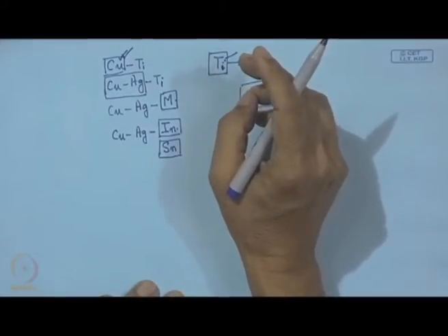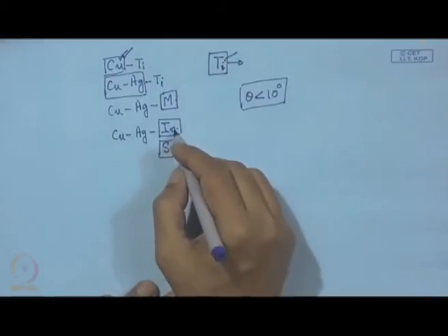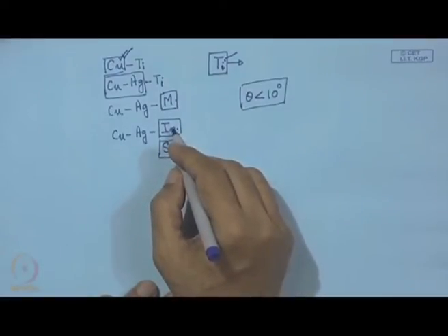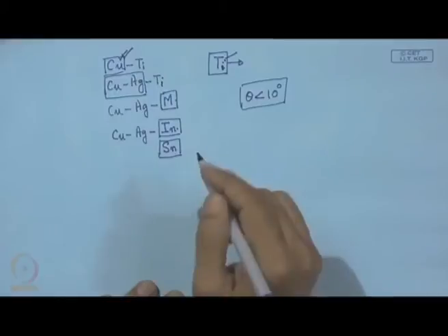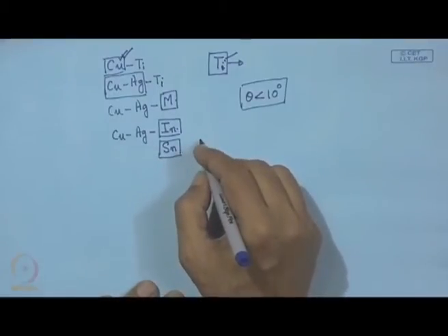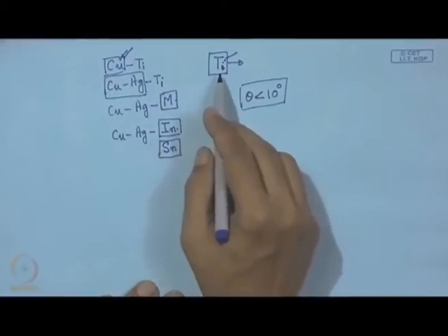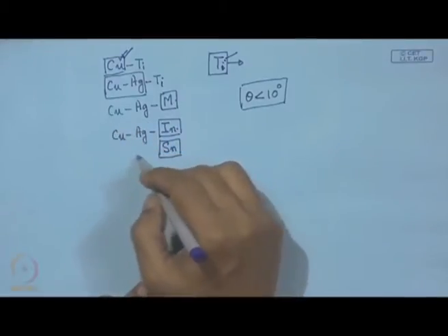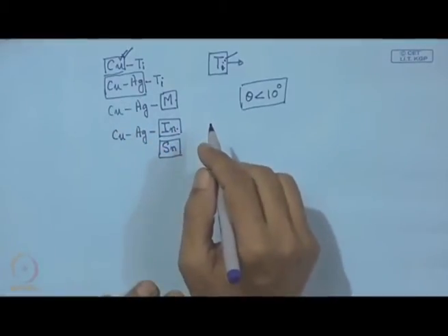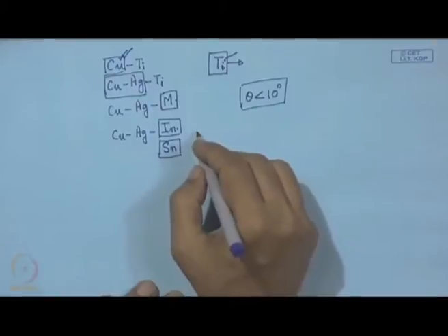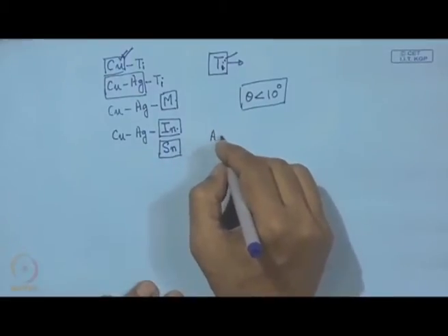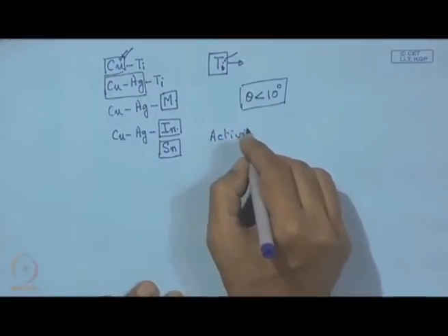Exactly what does it mean? When we add indium in this system, what happens? The solubility of titanium in this alloy decreases, and thereby the activity of titanium increases.